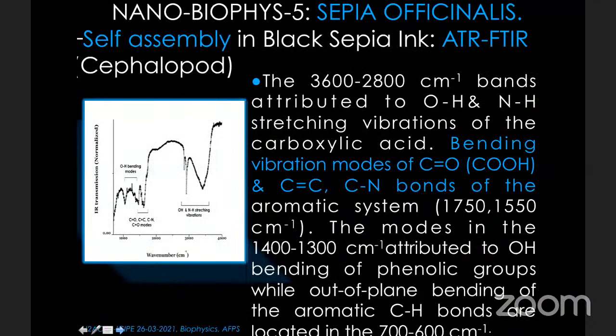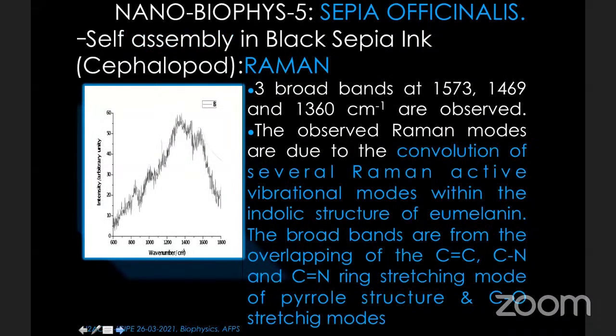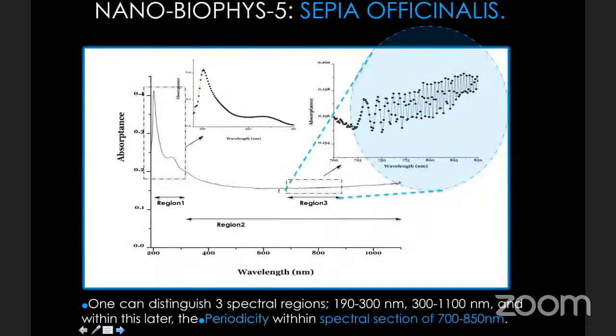The most important thing here is that black ink is due to light trapping, and we wanted to find out what's the reason for which it traps light. And we have investigated, of course, with the physical methods, an armada of them. We have found that indeed its absorbance is not very high, but it's very, very broad. It's high in the UV and the blue, and it's quite constant in the visible to the near infrared.